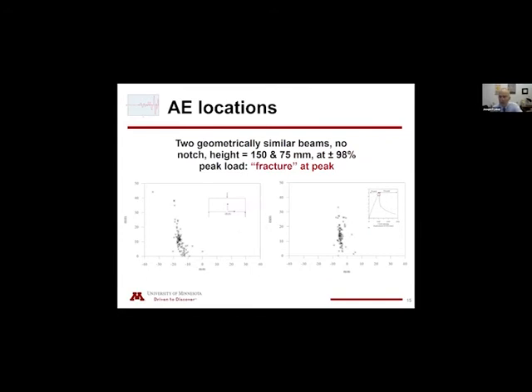These are, again, the same results. This particular beam was of 75 millimeter height. If we test the same material, similar geometry, but double the height, this beam now is 150 millimeters in height. I would argue that the picture of this clustering of the events, again, around peak load is very similar. So this fracture, at least for this material, for these size beams, is developing in a similar manner.